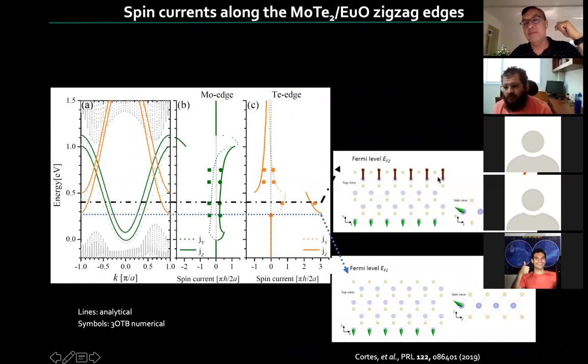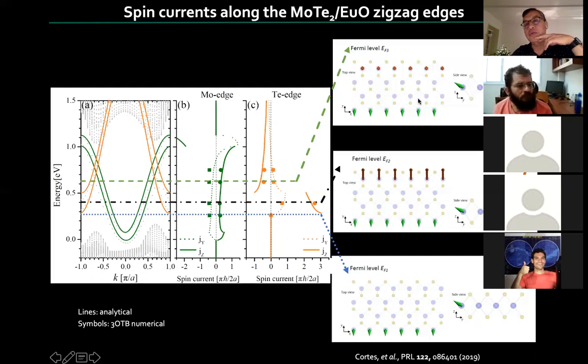on the moly is relatively the same, but the tellurium is now huge with a strength that you can see is rather large and tilted. Again, it's canted because of all this competition of the various spin orbits. Now, if I keep increasing the Fermi level, now I populate all of them. Now the two channels in the tellurium also compete with each other, and the cartoon is more like this, right? Where now I've decreased the current, changed the orientation of the spin, but I still have current on both edges. So the experiment to imagine is to deposit this on the magnetic substrate, put current contacts, and depending on the gate voltage, I will have transmitting current along the edges that has a value and an orientation that is in principle controllable by this gate.